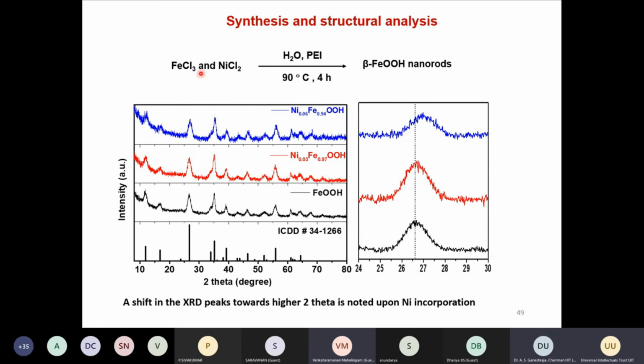We have taken iron chloride and nickel chloride, and PEI, polyethyleneimine, is used as a capping agent. This synthesis works better when we have the polyethyleneimine. In the absence of polyethyleneimine, it's a little complicated. The iron oxyhydroxide structure may not be completely formed. Getting a pure phase of iron oxyhydroxide is a little challenging.